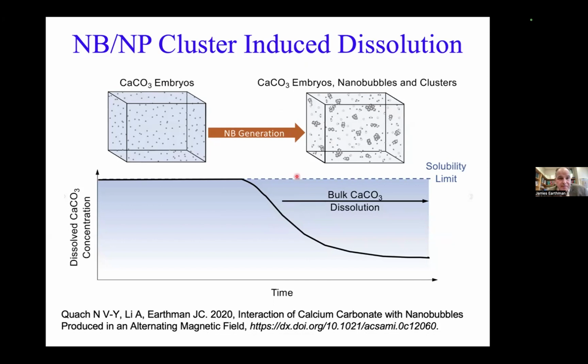You've got something at the solubility limit. That's typically where you're going to be in one of these surface water systems, because if there's more calcium carbonate in the water, it's going to deposit somewhere, and the concentration will go back down to the solubility limit. If there's not enough calcium carbonate in the water, then something will dissolve. The calcium carbonate will dissolve somewhere and bring the concentration back up. So you're typically around the solubility limit of that compound in the water when you have it depositing on the